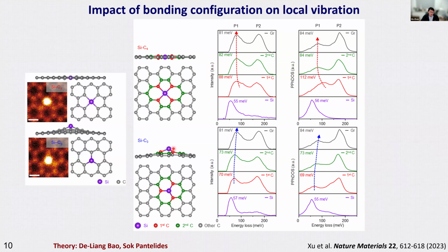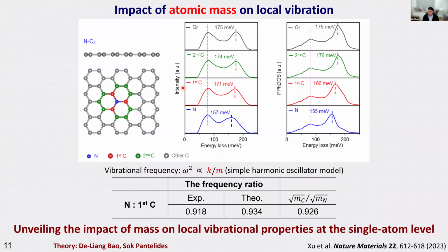So this is three-dimensional bonding, and this is a quasi two-dimensional bonding. And we see that the chemical bonding actually affects the local vibrational modes, and we have the sensitivity to pick it up. And the other factor, as I mentioned, affecting the vibrational frequency is the mass. So in this case, we change the impurity atom to a nitrogen atom, and we can pick up the spectrum from the nitrogen atom and from the neighboring carbon atom.